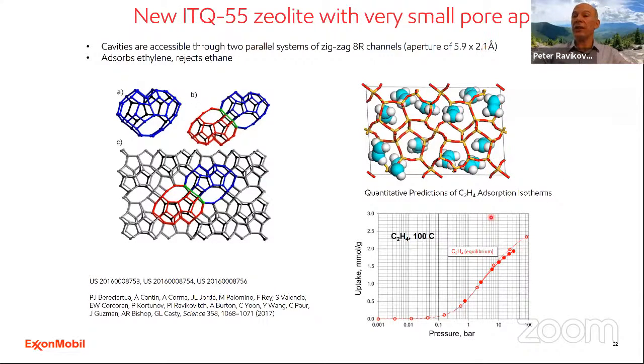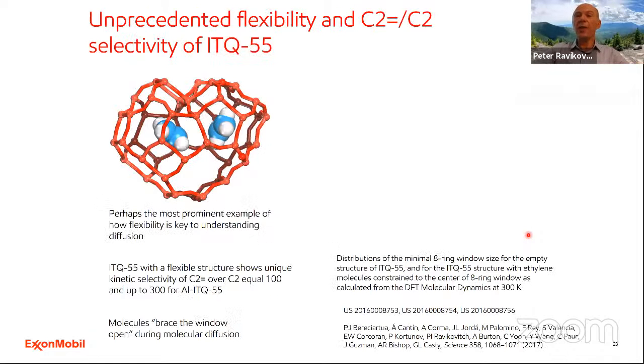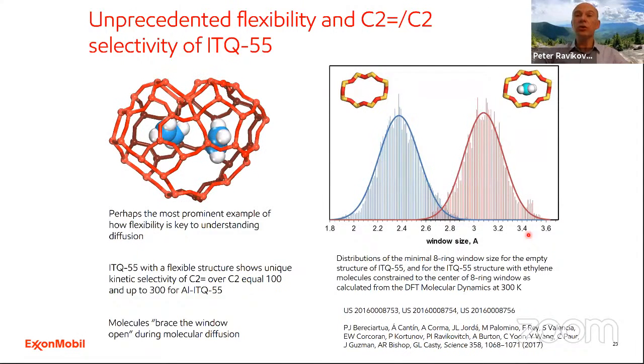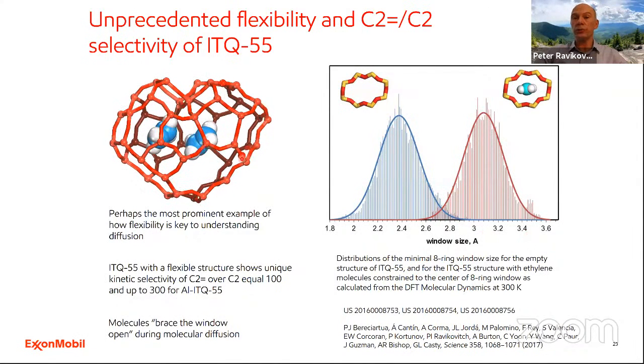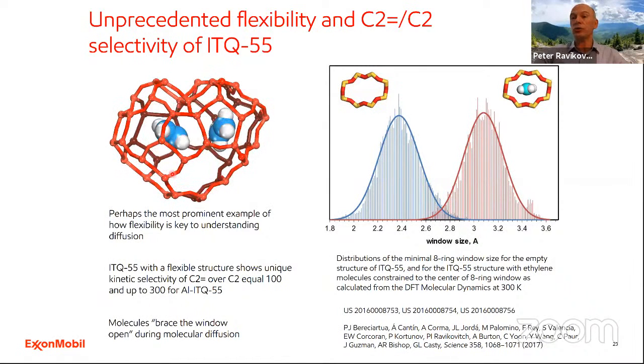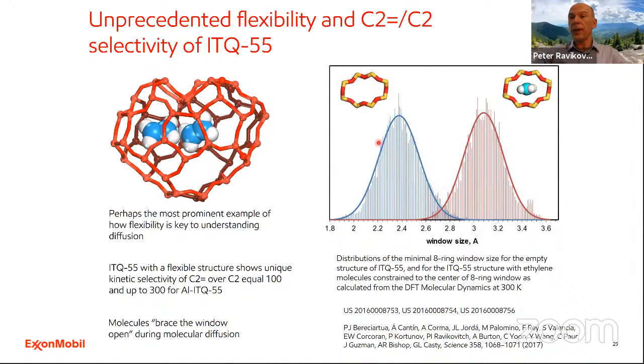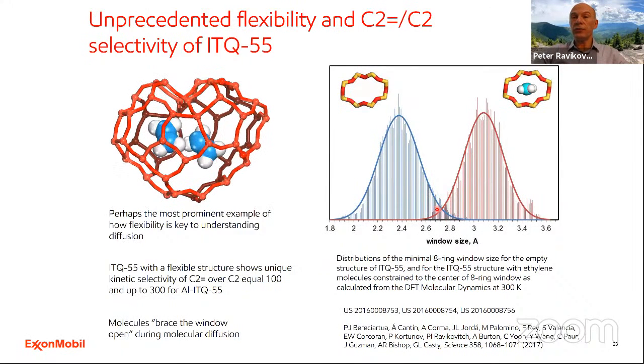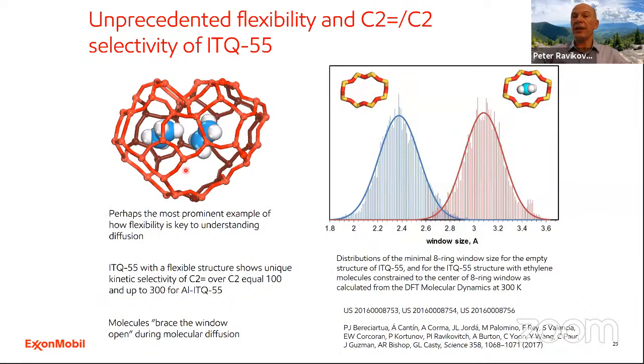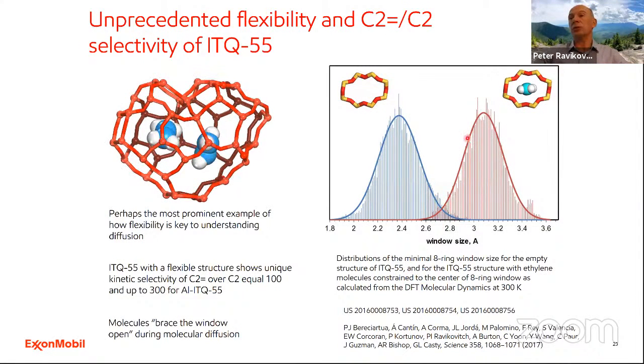Nevertheless, the material is able to separate, for example, ethylene from ethane, and these molecules are quite a bit larger than the size of this window. You can see here the equilibrium adsorption isotherms predicted in agreement with experimental measurements. But during diffusion, what happens is that if you look at the histogram of window size distribution for the empty structure, it is this one, blue. But when ethylene diffuses through and goes through the transition state through these 8-member ring windows, the structure expands by about 1 angstrom.